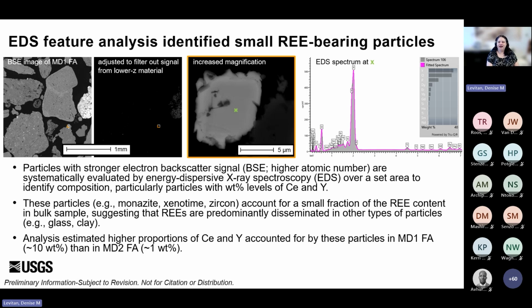Based on what we know from previous studies from the literature and also work that Alan has done previously, the rare earth elements in CCR tend to be dispersed within those aluminosilicate glasses, those little spheres that we saw in the MD2 fly ash. But as you may have noticed, those spheres don't exist in MD1. You can kind of see here that the minerals didn't fully melt and form those glasses in MD1 in the CFB with the lower temperature. So the rare earth elements can't be trapped in those. They don't exist. And so what that suggests then is that they are disseminated, so not concentrated, but within other minerals that exist in MD1, again, based on the literature, likely some of those clays.